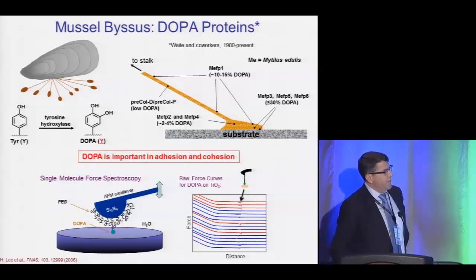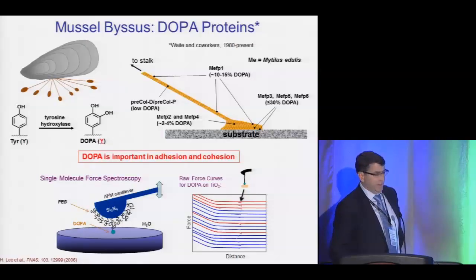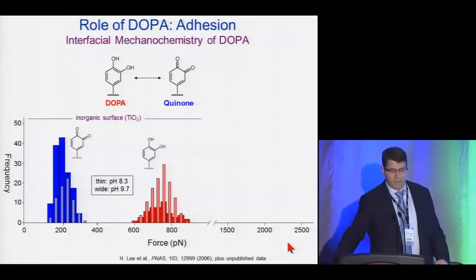And we can do this experiment many times. Under certain conditions, we could do it many times. We could take the cantilever off, put it back down, and that's exactly how we generate this data that you see here, which is all obtained from a single cantilever, okay? Which means that we can generate force histograms. And from this experiment emerges one of the interesting features of DOPA, which is the equilibrium that exists between DOPA and its quinone form. And that's shown up here.